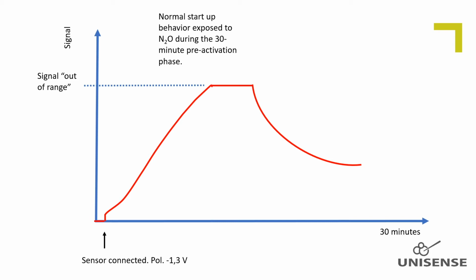This graph illustrates the signal from a nitrous oxide sensor during the time of pre-activation. Right after turning the polarization to minus 1.3 volt, the signal starts rising due to the reduction current and could reach an out-of-range current. After some minutes, the current starts to decline to some 100 picoamps, and after 30 minutes, the polarization is adjusted to minus 0.8 volt. The baseline goes down and will stabilize on a low level, typically below 10 picoamps.